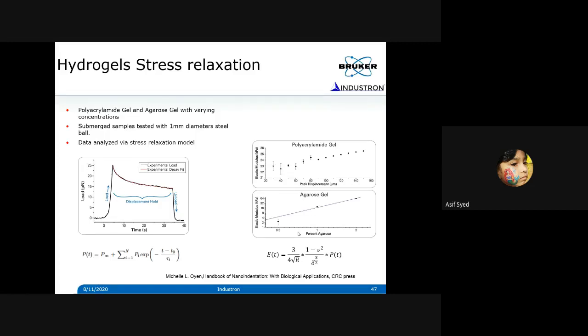Okay, that's what I'm showing in the loading curve, and then keep the displacement constant. Which means that the feedback is fighting to keep the displacement constant, and you measure how the load is relaxed. You can measure the load relaxation as a function of time. Now you can take this load relaxation curve and fit it to a model. This was developed by Michelle L. Oyen, and you can extract the modulus of the material from this relaxation curve.